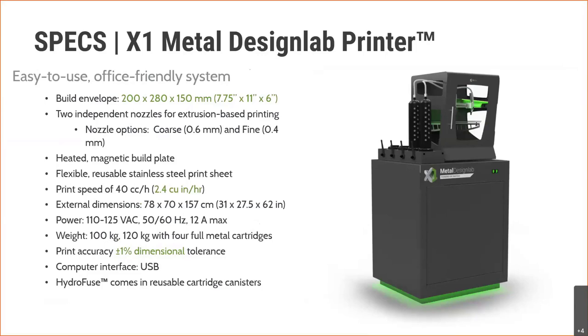Typically with the MIM process, the shrinkage winds up erasing some of that accuracy in terms of the dimensional accuracy, but we guarantee plus or minus 1%. So what that means is that if you print a part that's, let's say, 100mm square, then you're guaranteed to have between 99 and 101mm every time you print. So that's actually pretty good for this kind of technology.